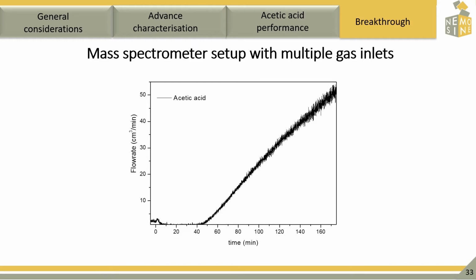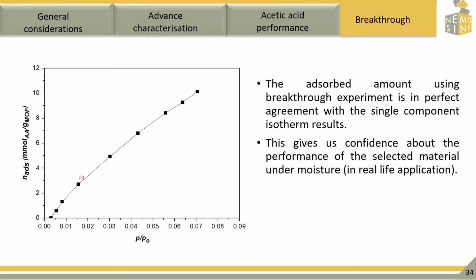Here we can see a typical breakthrough curve. Actually, this is a result of a material that has very high affinity for acetic acid. As we can see, for the first 50 minutes, no acetic acid is detected, which indicates that all the gas is adsorbed by the material, even with the material being kept at a moisture level of 40%. The acetic acid signal starts to appear upon saturation of the column. From the breakthrough curves, the adsorbed quantities can also be determined, since we know the flow rate, concentration of the acetic acid, and the time that it takes for the saturation, so we can calculate the amount that was retained inside the material.